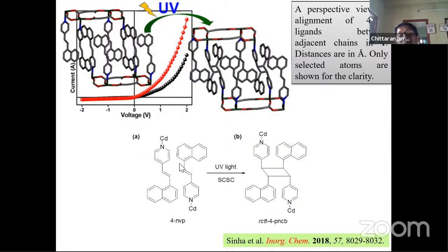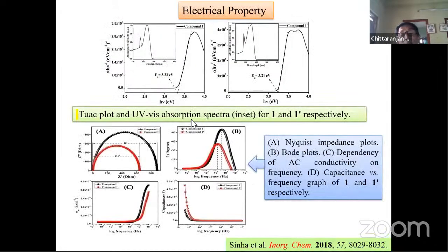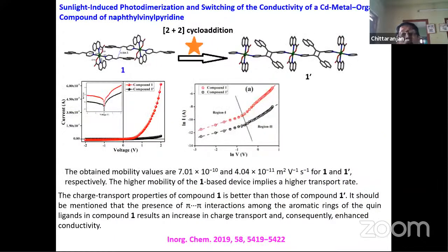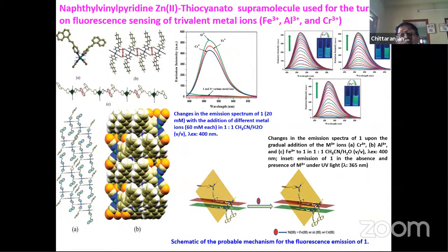This olefinic polymer shows better conductivity than the cyclobutyl polymer, and it is observed from the current-voltage diagram, and also from the I-V plot, and from other directions. Herein you can see the same thing for the cyclobutyl derivative, in the current-voltage diagram, log I log V, there is an inflection point, and after that Schottky diode behavior is observed, but its mobility is quite less than that of the previous one. Herein another molecule, this naphthyl vinyl pyridine system, shows this conductivity along with sensing activity.